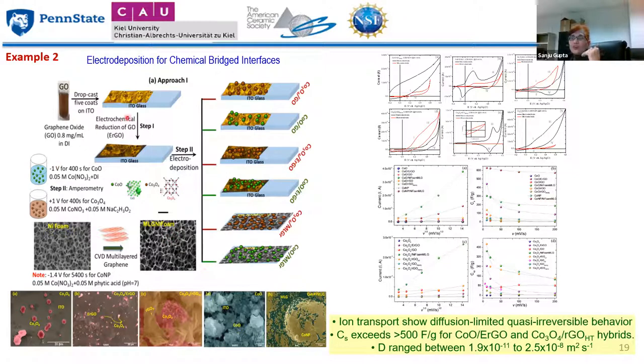So we have a whole range of these nano cobalt oxide, CoO, Co3O4, and even cobalt nanoparticles. Some of the SEM images you can see here. And interestingly enough, we found that we can have faceted cobalt nanoparticles or cobalt oxide nanoparticles using this strategy. And then we in fact also use the electrochemistry to reduce our graphene oxide platform, because our starting material was the GO, which we transformed into either RGO or ERGO, as we call them. And then we measure the performance in cyclic voltammetry, as you can see here.